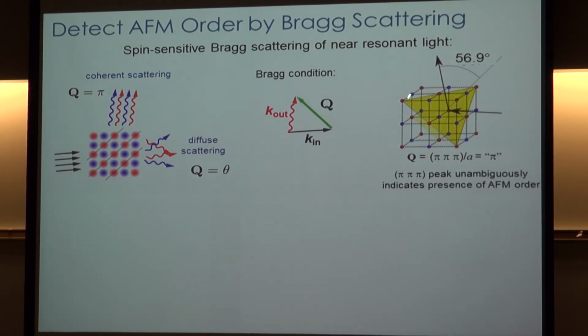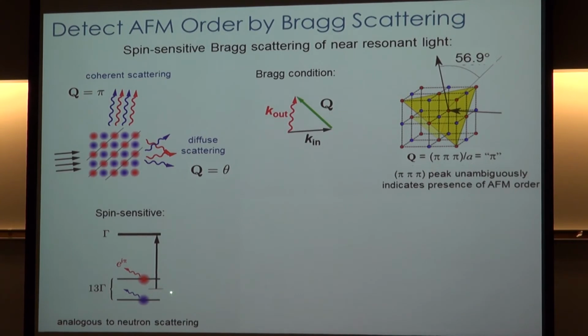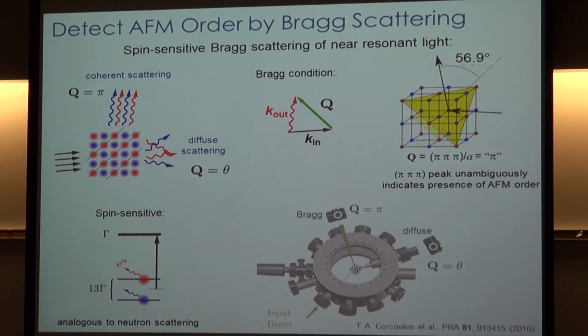So this is shown a little bit more schematically here. And again, this is the reciprocal lattice vector, which is sensitive to the antiferromagnetic order. Now we make it spin sensitive by tuning our probe laser in between these two spin up and spin down states that I described earlier. And so you can see that there's going to be a phase shift of pi between the scattered light from spin up and spin down. And so we can be spin sensitive in that way.